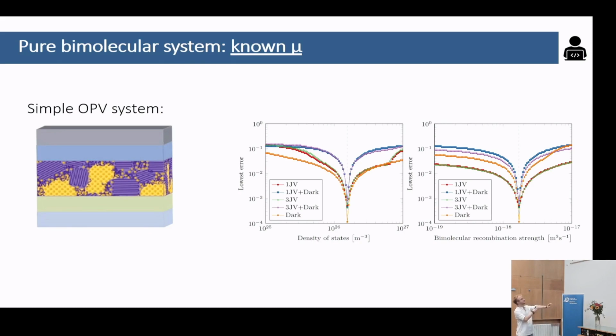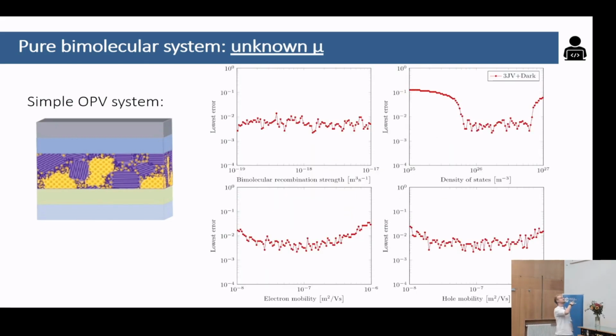Here I'm plotting the RMS error versus two different parameters, the effective density of states and the bimolecular recombination strength. And if you really take those, here you have a narrow range with a single parameter. So if you only have two parameters, you can get both of them very precisely. But here you have to assume that you already know the mobility. If you don't know the mobility, this is what you get. You have so many of them that could work.